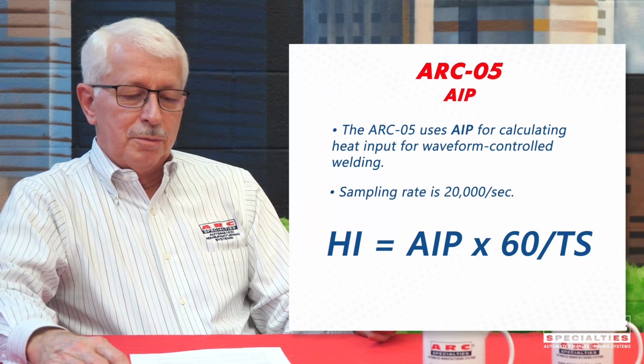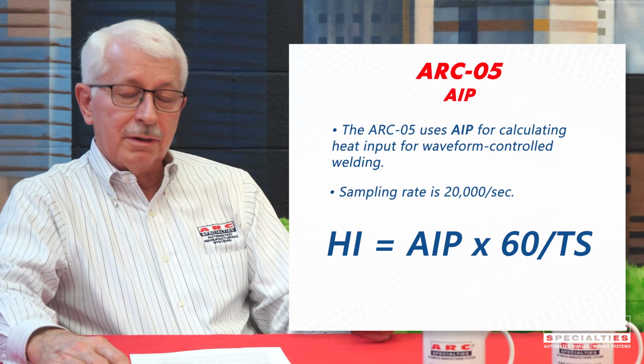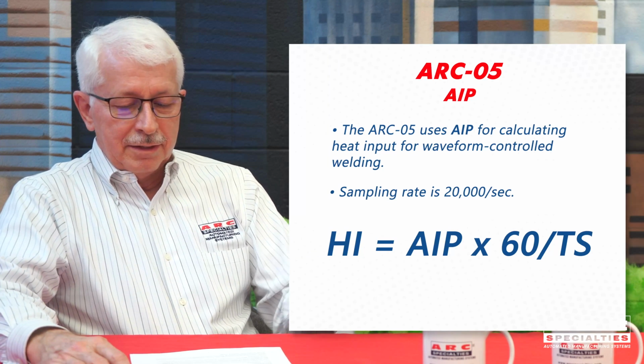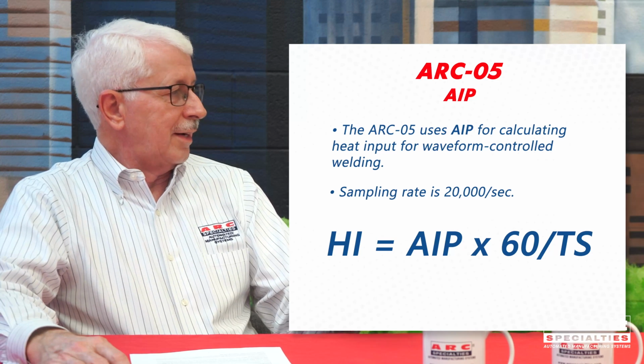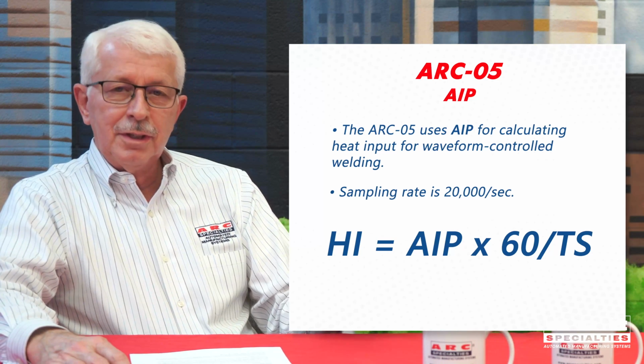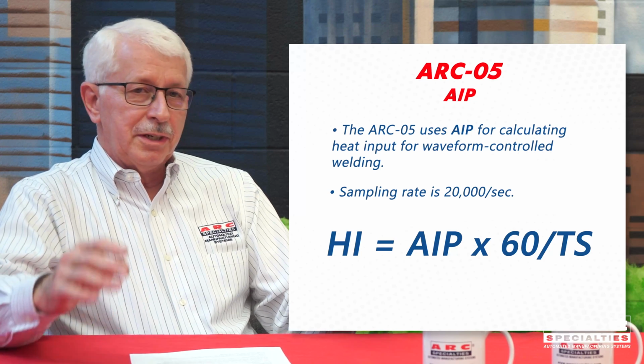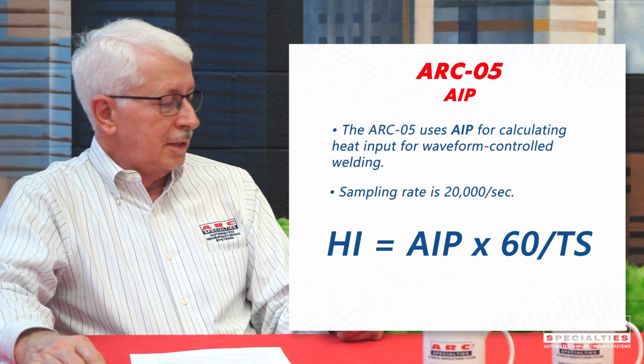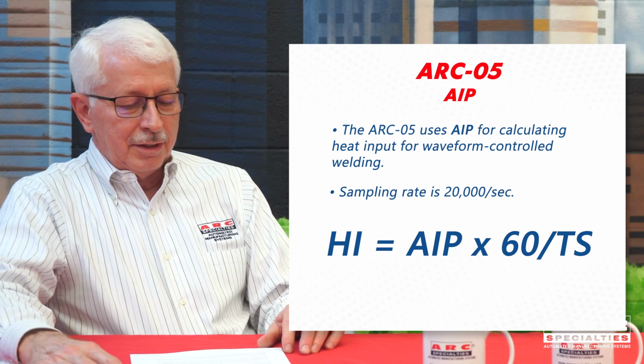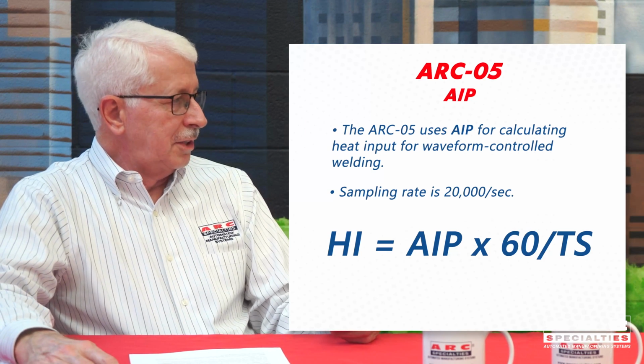And we're using the formula for average instantaneous power. So we're taking the average of the sum of the products of amps times volts. We know our travel speed, so we know time and distance. And so we can calculate and display average instantaneous power. Okay, when we're talking about instantaneous energy and power calculations, it's really intended for waveform-controlled gas metal arc welding in the pulse mode.